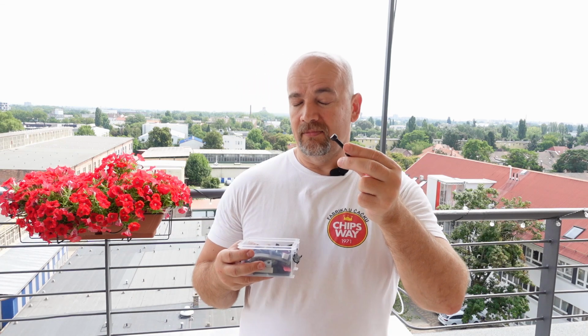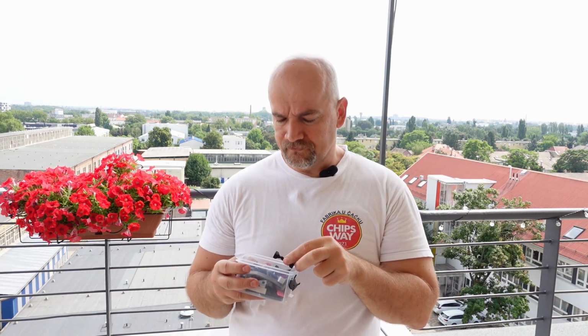PETG. My first impression was when I saw the temperature tower that it is very nice, very printable material. But later I was a little bit disappointed in this material's tests. First, it is the most brittle from the tested materials, but it should be more tough compared to the PLA. And also that heat deflection temperature just a little bit above the PLA, so approximately 60 degrees Celsius. That's not enough for the PETG. It should resist 70 or 75 degrees Celsius.